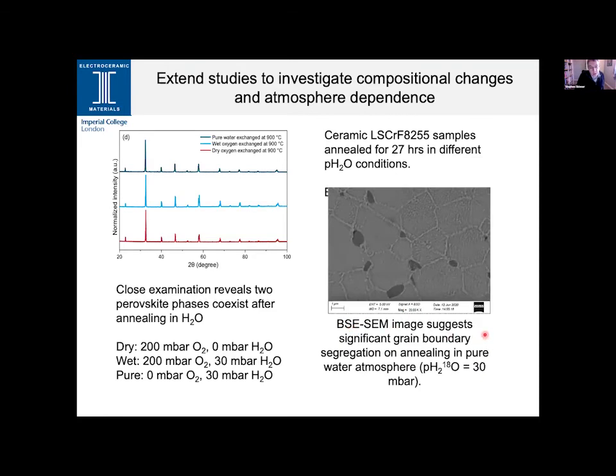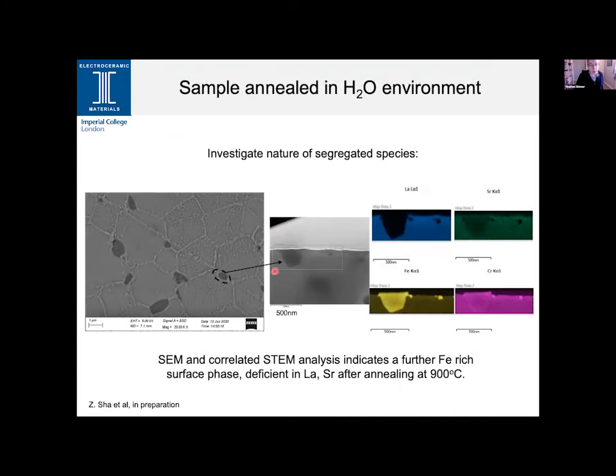Further to that, we also observe from the backscatter imaging these contrast features in our micrographs. So turning to some STEM analyses, we were interested in identifying what those species were. From the segregation, we looked at the cross section in the STEM analyses, and this is a 500 nanometer scale bar. We can see a clear feature in this subsurface. And from that, using some STEM EDS, we can see that it's clearly lanthanum deficient, clearly iron rich, and slightly chromium enriched. So there is a segregation of a third phase, an iron chrome phase, which may well be of the spinel type.